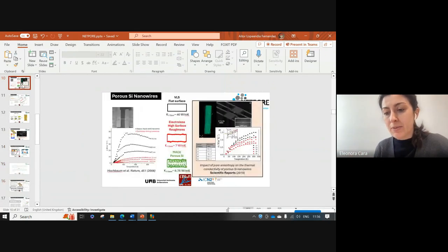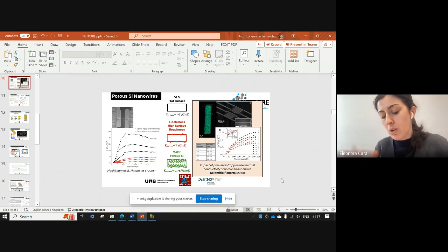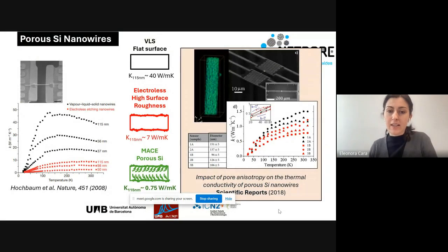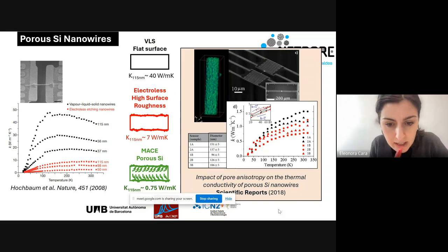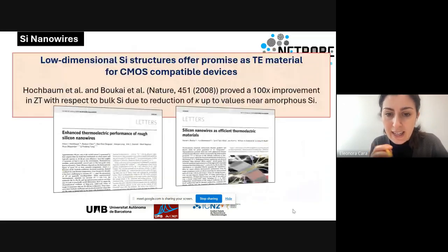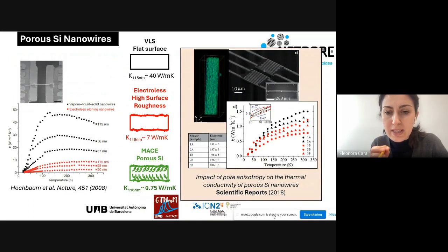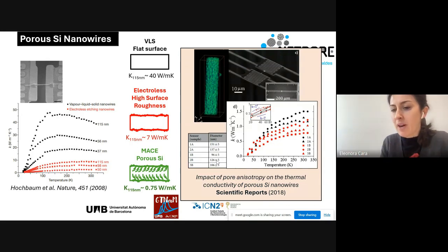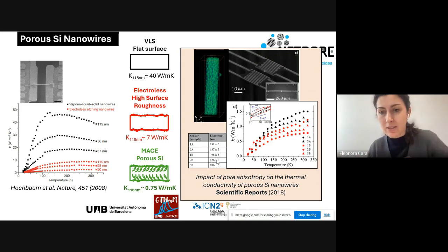We have not played so much with different porosity content, so we have used in this case N plus doped silicon as a starting point, and we know that as compared to low doped silicon, it gives higher porosity in the nanostructures, but we have only modified the actual diameter of the whole nanowire. So in this slide that Aitor is showing, the thermal conductivity was measured against nanowires with different diameter. So there is actually a dependence of the thermal conductivity on the diameter. For instance, in this same article, if I remember correctly, there is another graph that shows how it is not dependent on the length of the nanowires.